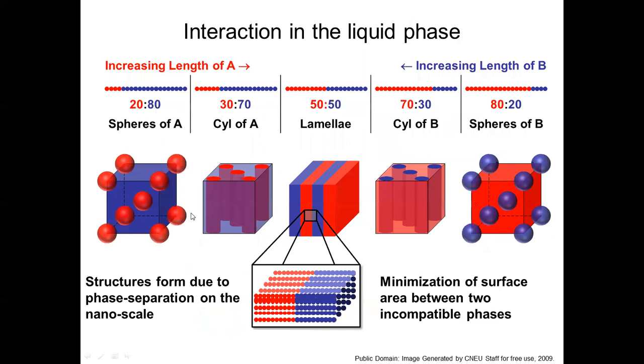So when we take a look at this and we do a formation, a spin, this is a liquid, we spin this on a substrate, allow this to reach a thermodynamic equilibrium. And what we're going to do is form these specific patterns. These patterns are indicative, again, of the ratio of PS to PMMA. Now we can use this patterning to our advantage because it has self-formation, and it takes very little infrastructure or energy to make this. We would pour this on the substrate, do a spin, and then potentially an anneal.